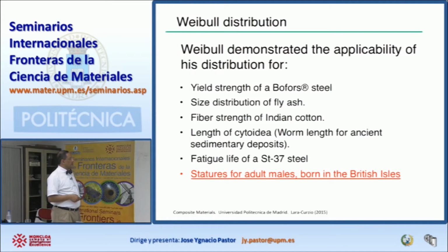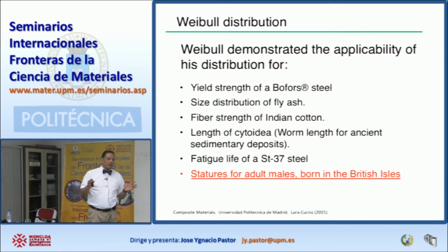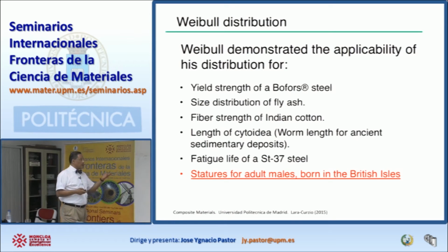And then in his company, they were measuring the fatigue strength of a type of steel. And he showed that his distribution did a very good job describing that distribution of fatigue lives. And not only that, I showed you that the Centers for Disease Control in the US had found a distribution of height for males using a normal distribution. In fact, in his paper, he shows that if you look at the height, the stature of males in the British Isles, that distribution of heights could be described with the Weibull distribution. So, this was beautiful, a very simple distribution, mathematically very easy to track, and it could describe a lot of different phenomena in nature. Okay, nothing fundamental about the Weibull distribution. There's really nothing written in nature for why this distribution should do such a good job, other than it does a very good job.